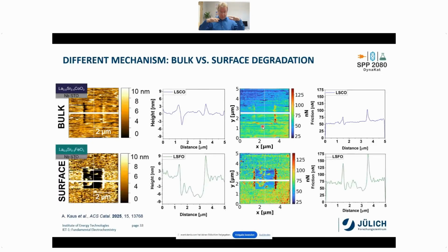So now we have a surface film that is growing, also shown by spectroscopy methods. So if we see this square, it has a completely different color. We can measure the height. You see here, there's a clear removal of the material, and also in the friction channel, we can now prove that it must be a different material from the bulk setup as well as what comes on top of the surface. So we can really follow these differences in the mechanisms here. Also with friction force microscopy, which is more difficult than with other techniques.